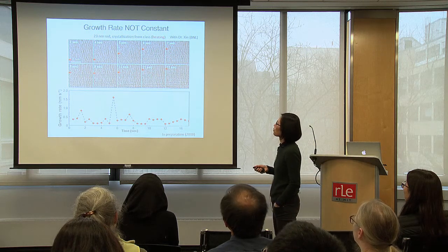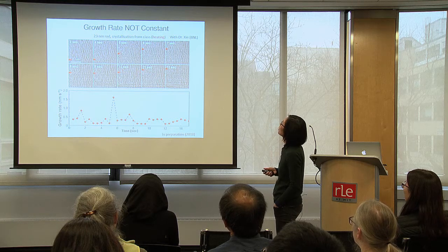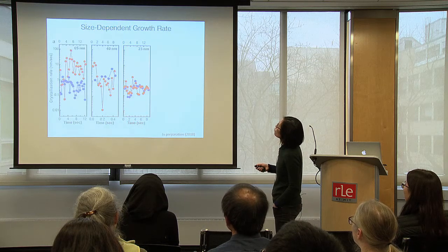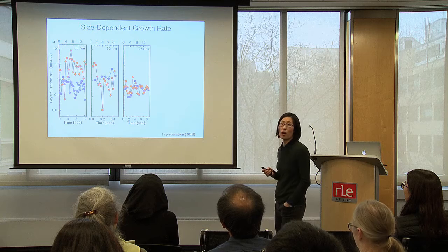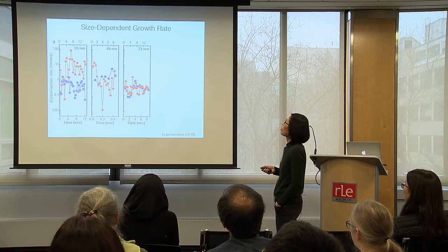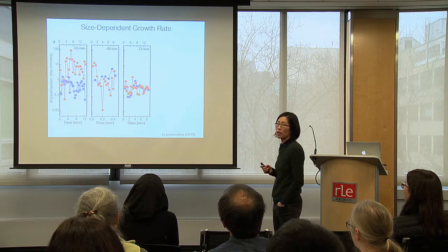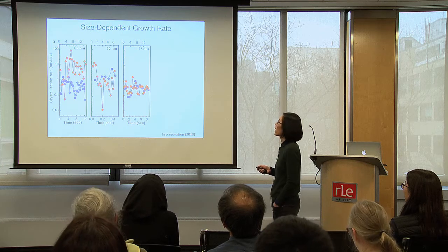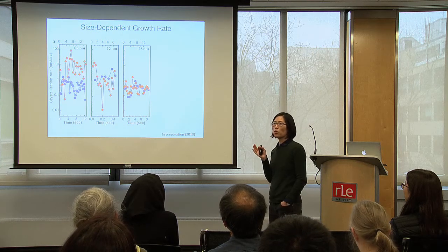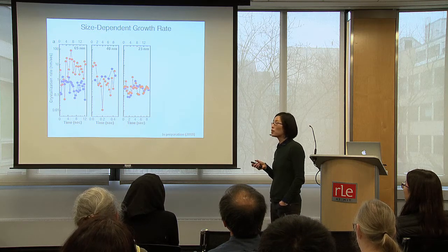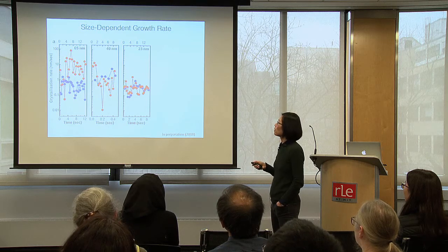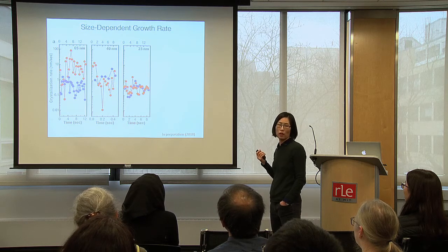So here's the growth rate we can measure as a function of time. So we can do this for different sizes of the rods. These are all isothermal experiments at the same temperature. Again, even though these are isothermal experiments, growth rates are all over the place. Okay, they're not the same.